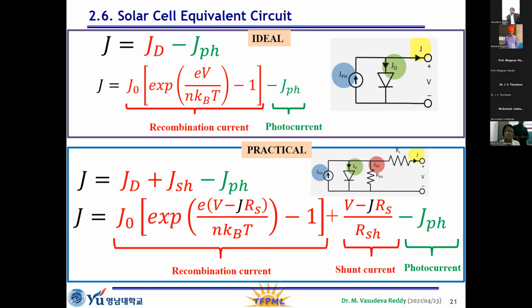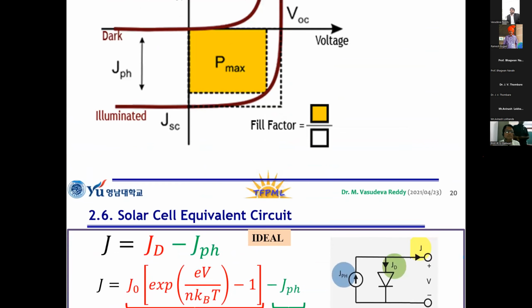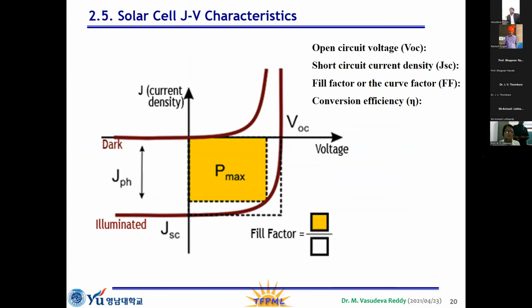For a solar cell application, the series resistance should be as low as possible. The shunt resistance should be almost infinite, as high as possible. These are the two important things. One more important factor is that we should achieve as high a fill factor as possible, practically 80% to 90%. We should also achieve as high a VOC and JSC as possible. This VOC and JSC depend on the active material in the solar cell. Particularly, the VOC depends on the band gap, and the current density also depends on the band gap of the material.